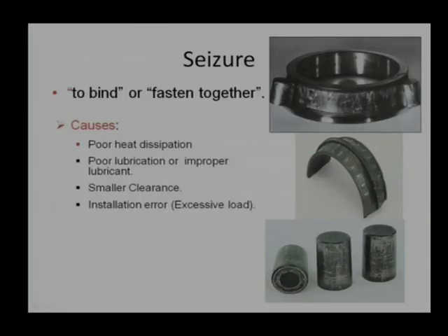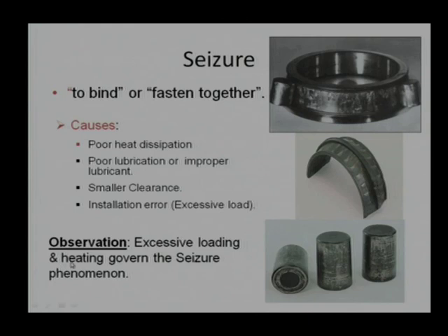This is one of the most common causes of failure, what we call an installation error. If the components are not installed properly, if assemblies are not fitted properly, if there is a misalignment, there will be excessive load on one side. Excessive load and high stress concentration at that point will increase the coefficient of friction significantly, and that will lead to a high temperature which finally stops the operation by seizure. Right? So, what we say? Observation: there is excessive loading and heat which govern the seizure phenomena or excessive adhesive phenomena.